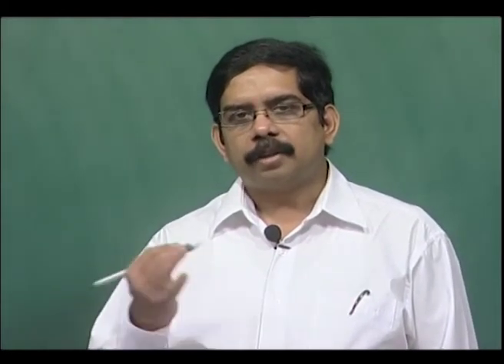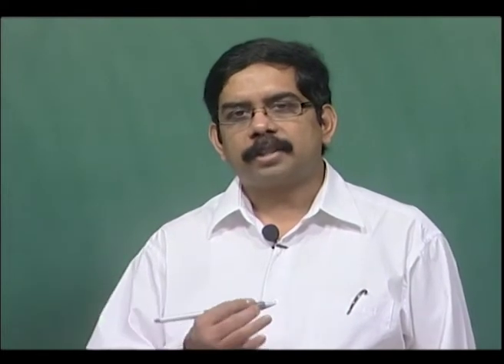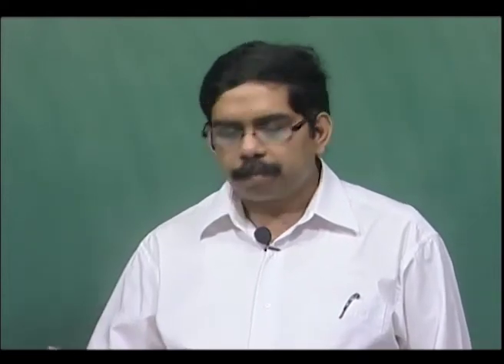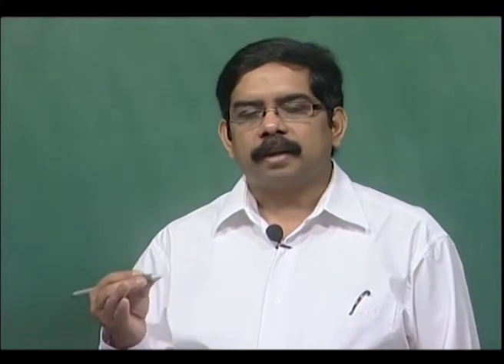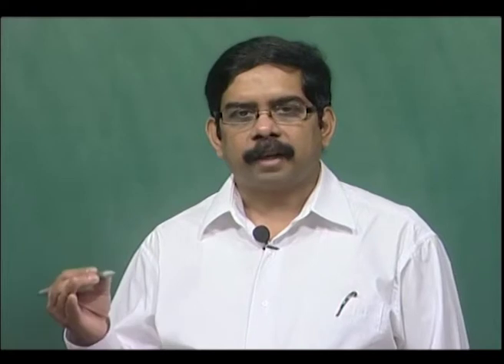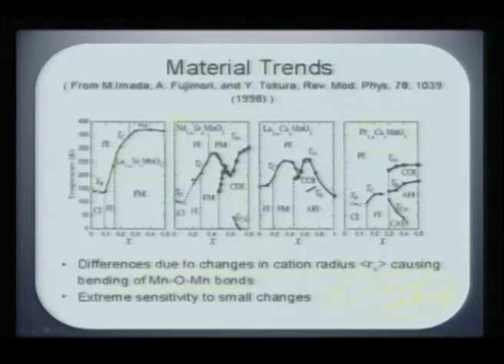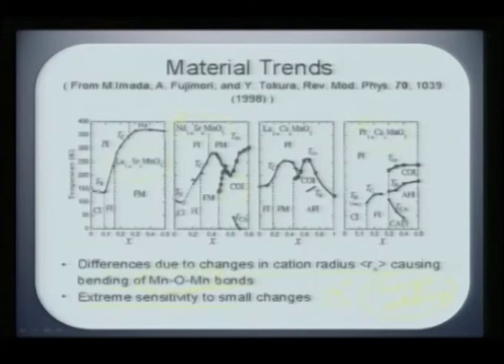which causes a double exchange mediated ferromagnetism and a super exchange competing magnetic ordering, which will actually bring about a charge ordered state. The super exchange mediated ordering leads necessarily to an antiferromagnetic state. The double exchange mediated ordering leads to a ferromagnetic state, and because you are distorting this Mn-O-Mn bond, you are actually going into a situation where it is charge ordered. In other words, there is a sudden twist in the Mn3+ and Mn4+ orbitals and they become orthogonal. As a result, there is no collinear magnetism and there is no exchange transport of electrons. As a result, the system suddenly transforms to an insulating state. Okay. So, it is an extremely sensitive composition to small changes which brings about such a drastic change.